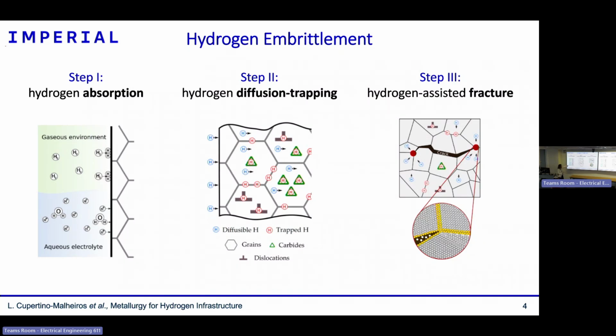Okay, so this is the first step, hydrogen absorption, and hydrogen can enter a metal surface when the alloy surface is exposed either to aqueous electrolytes, and that can be even the atmosphere, because you have water vapor, or a gaseous environment, so H2 gas, that is more relevant when we are talking about hydrogen gas as a green energy.